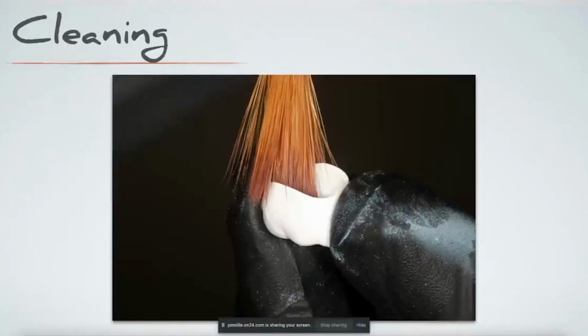That white dust on their gloves is inside those crowns, and if that's not cleaned out well, when it fires, it'll leave this kind of weird chalky appearance on the crowns. Now, you can use air to dust this off, but I would warn you that you need to make sure, one, that the airline is totally dry, with no moisture. Because if there's any moisture contaminating this restoration, when it goes to fire, it will fail. It'll crack and it'll split. It needs to be totally dry.